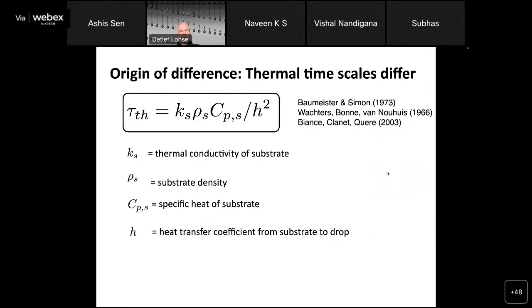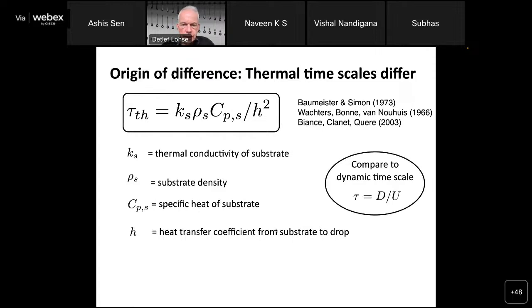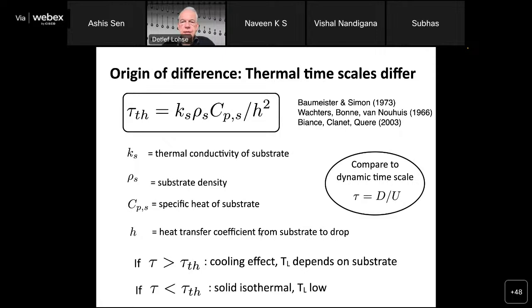So the origin is that the thermal timescales differ, and the thermal timescales, in fact, are known since the 70s or even the 60s. There's this very nice paper from 1973 where they calculate the timescale for the thermal timescale, which is in fact composed out of the thermal conductivity of the substrate, density, specific heat of the substrate, and the heat transfer coefficient from substrate to drop. And this timescale must be compared with the dynamic timescale of the impact, droplet diameter over the velocity. And if this dynamic timescale is larger than the thermal timescale, then you have a cooling effect, and then the Leidenfrost temperature should depend on the substrate. If this guy is smaller, then there should be some independence and you have some ideal substrate.